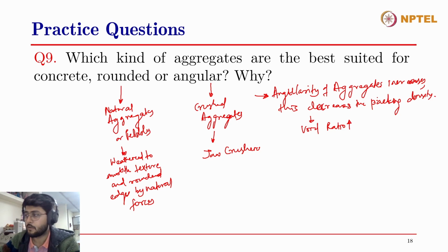What I'm trying to say is, in order to increase the packing of the aggregates, you have to use different sizes of aggregates. So it has to be a well graded material, so that the lower sized particles take the voids while the higher sized particles maintain the shape. On the other hand, if we are talking about the same size of aggregates, then angularity increases the void ratio and decreases the packing density, whereas rounded aggregates of the same size provide the best packing, right?